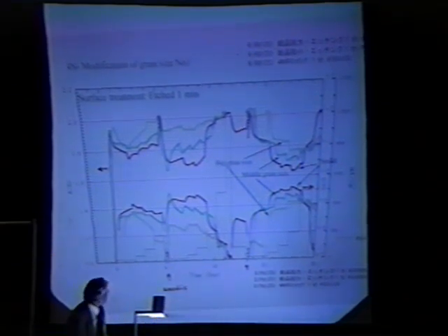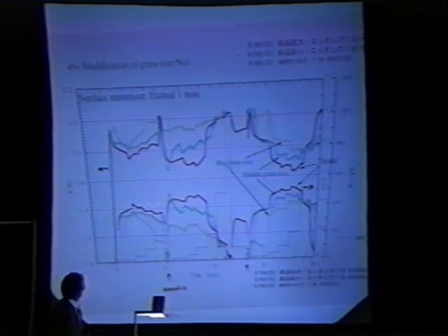This figure shows the loading experiment. The upper side is the R over R0 change versus electrolysis stage and time. Looking at the final stage of the loading, the difference among the three grain sizes is obviously observed. The small size is better than the larger.